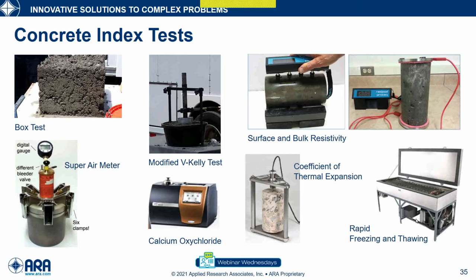Depending on the property of interest, the top left is a box test for workability. The super air meter is a measure for durability and the distribution of air within the concrete mixture. The modified Kelly is a measure of workability. You can do a calcium oxychloride test to see how the cement is affected by chlorine and other deleterious materials that enter in. The freezing and thawing test, and then top right are some resistivity tests. Again, resistivity is a measure of how water and other chemicals can transport through the concrete itself.